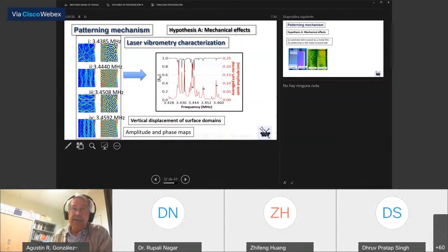Actually, if you examine by laser vibrometry, these are experimental results, the surface of the piezoelectric substrate with the film on top, you can see that there is this vibrating oscillation, as you can see here in this vibrating map, amplitude and phase map corresponding to the surface. There is a very strong dependence on frequency, that's clear, but you can see that changing the resonant frequency and moving along this map of resonant frequency of the device, we can induce oscillations which are considerably high, in the order of 3-4 angstrom of movement of the atoms. The surface is completely vibrating. So this is perhaps the most likely hypothesis.